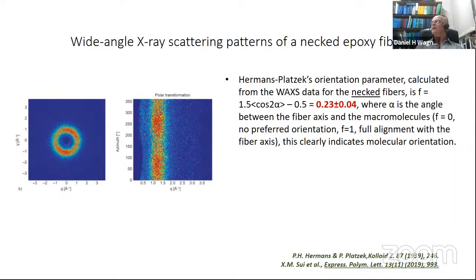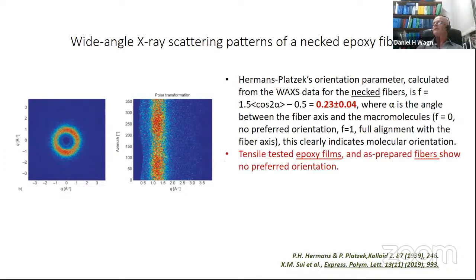negligible. Okay, if you had a value of 1, you would have full alignment with the fiber axis. And of course, you cannot have that in epoxy, which is cross-linked. But nevertheless, we get molecular orientation. We are currently busy doing many more tests, both mechanical and spectroscopic with WAXS and other techniques. And we are also using epoxy films and fibers,